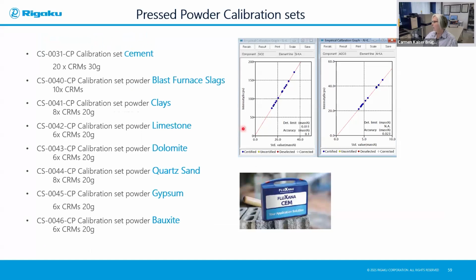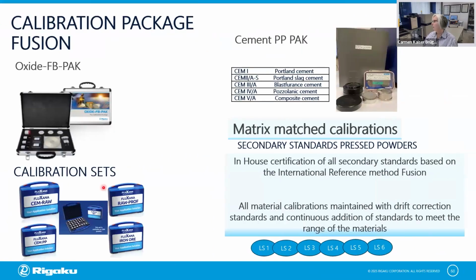The other examples of pressed powder calibration sets, not only cement, but we can have slags, clays, limestones, dolomites, sand, gypsum, and bauxite as the pressed powder. So I have shown you now pressed powder and fusion calibration standards that are available, but we can also help you with doing matrix matching calibration. So if you buy a new spectrometer from us, we will work together with you to certify your reference materials, and these references are called secondary standards. So for pressed powder, this is very important, and therefore we can do this for you.